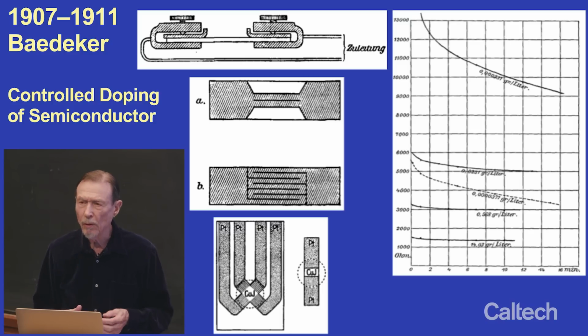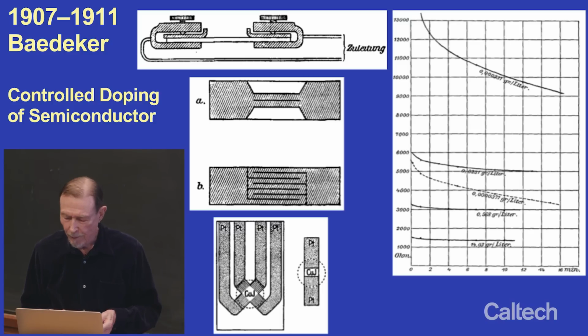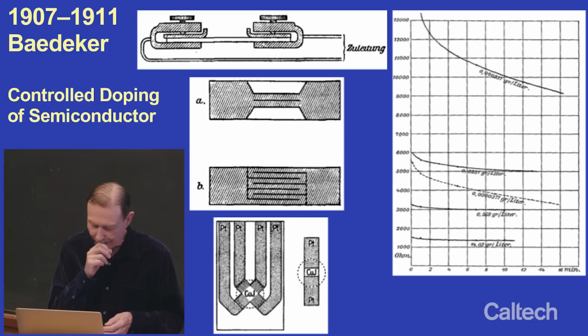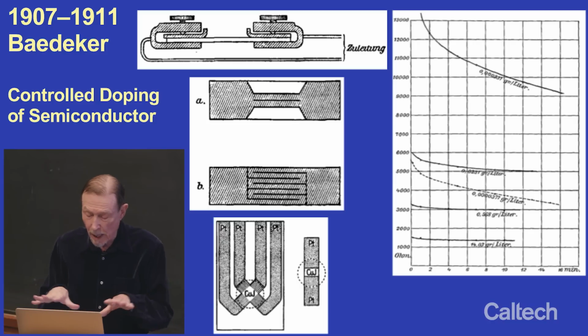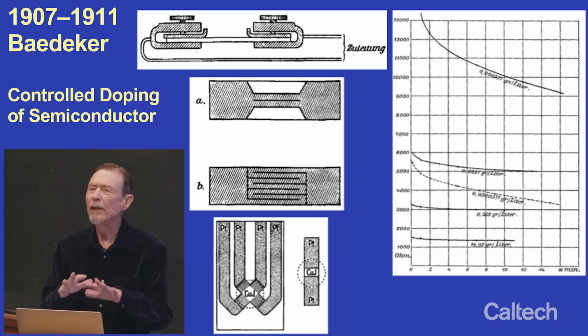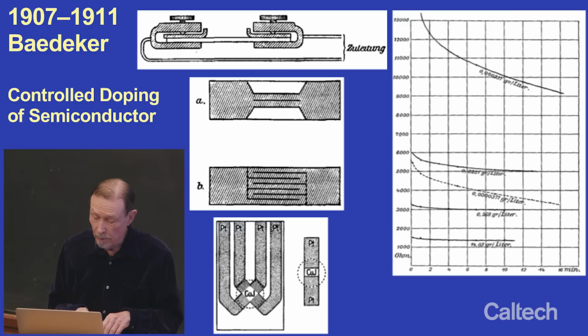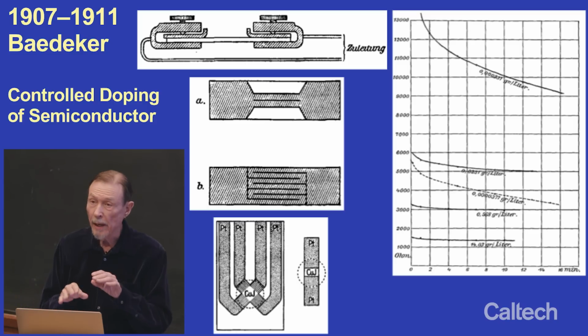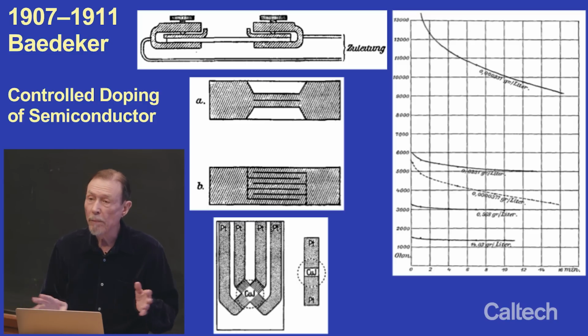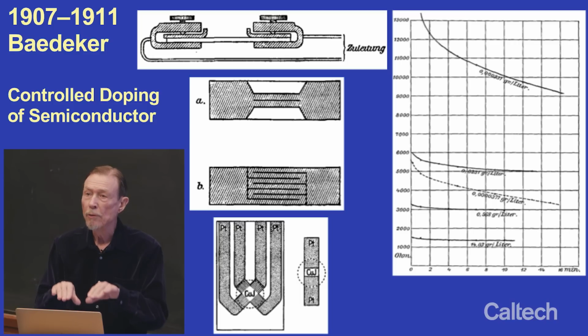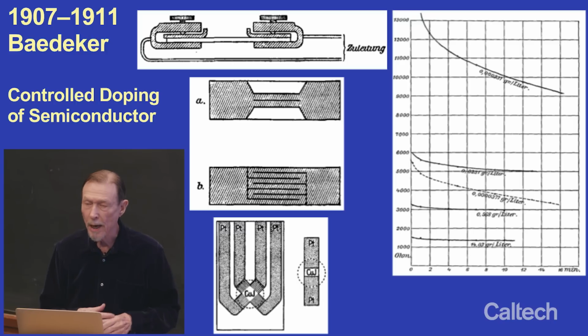And he developed a whole bunch of techniques. His most favorite one was copper iodide. You see that in the bottom picture. And he made contacts out of platinum. It had really good properties. And he found a remarkable thing with copper iodide. The way he made it, of course, is he vacuum deposited a copper layer, a thin film, which he could control the thickness of by how long you evaporated the copper on the glass microscope slide.